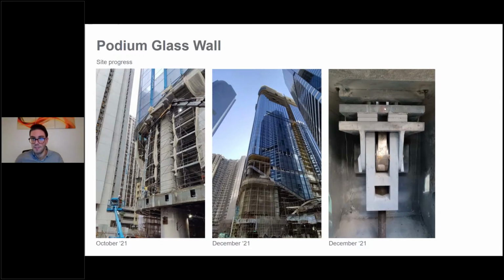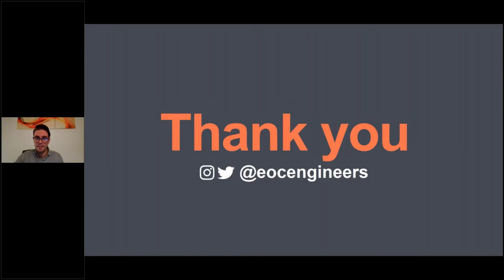Another thing that you can see here, probably not very clear from this image, but these things are load cells, because basically one of the requirements was that the pre-stress level in the rods has to be monitored permanently. So we have a set of 4 load cells for each of these rods, constantly measuring the tension and transferring the data to the central monitoring of the building through a wireless system. So basically, we have a live prediction and measurements of the tension in the rods, and a warning clearly will be given in case the rod pre-stress and tension level drops below a certain threshold or rises above some critical value coming from the design. And thanks.